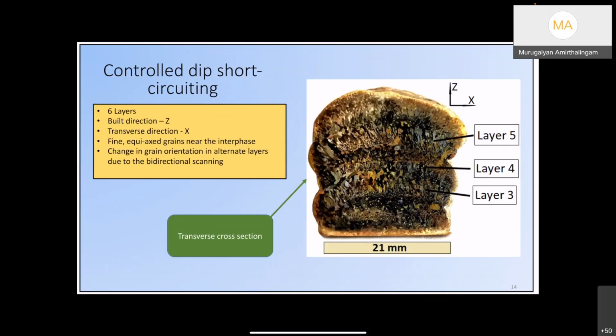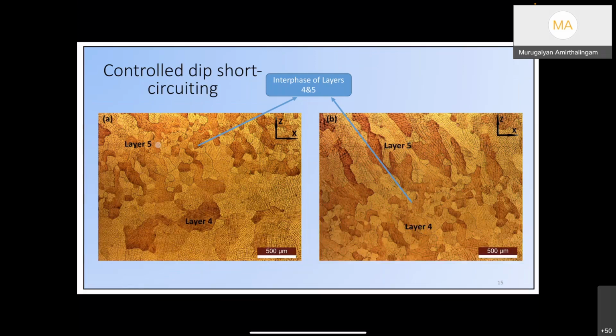But by changing the metal transfer mode, what we see over here is clearly a change in the microstructure from the planar solidification, because we now change the temperature gradient during solidification into a shallow temperature gradient. We do this by changing how the metal is transferred, and also optimizing the current to bring it to a much lower level so that the top and bottom temperature differences are minimal. And that leads to a complete change in the microstructure, isn't it? So what you see over here, compared to the last one, is more of an equiaxed microstructure.